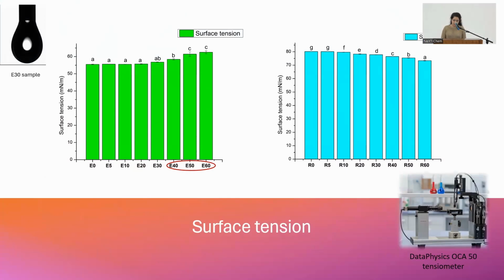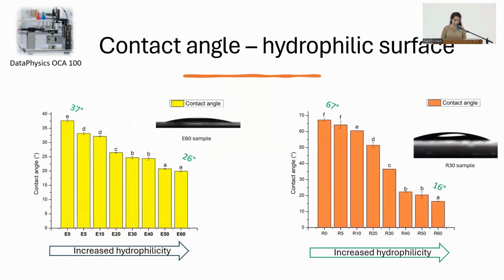The next analysis was the surface tension using the tensiometer from DataPhysics. In the case of ethylene glycol, we see in the first 5 samples a quite similar value, around 55 millinewtons per meter. And with the water concentration rising, we also have a rise in the surface tension. In the case of Reline, we have a decrease of surface tension with the increase of the water content.